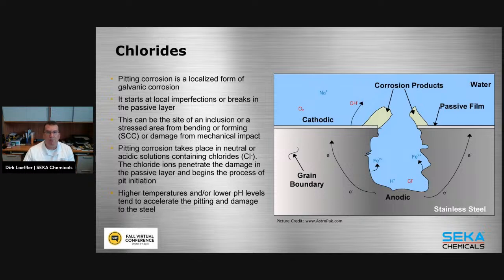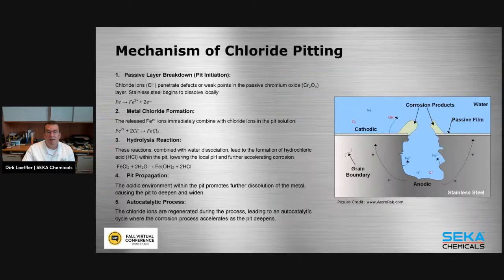Again, it can start at local imperfections or breaks. Now this becomes an area where pitting corrosion can take place. Chlorides get in there. Chlorides react with the iron and the water. Here we have our HCl already, ready to form. And again, keep in mind, this is much more pronounced at higher temperatures and or lower pH levels. This is why we generally see this a lot more commonly in acid CIPs or hot liquor tanks. Let's break this down a little bit further.